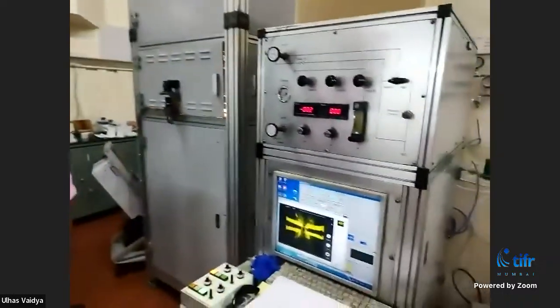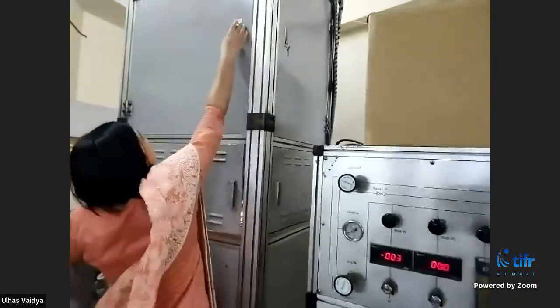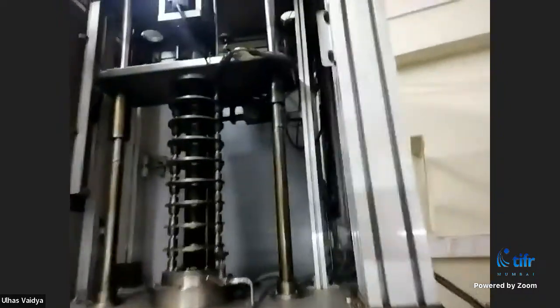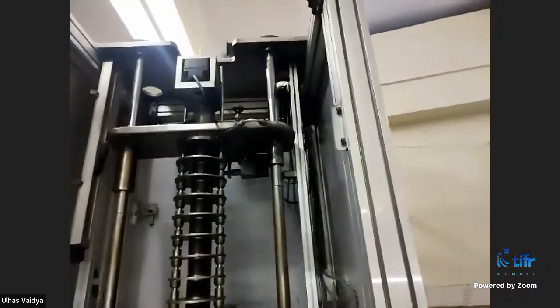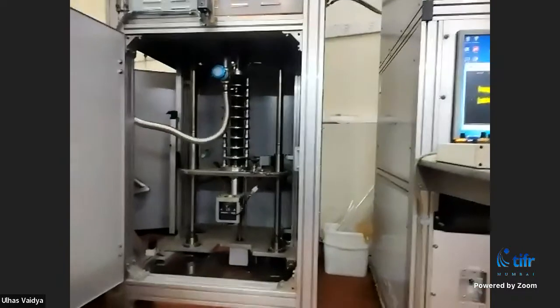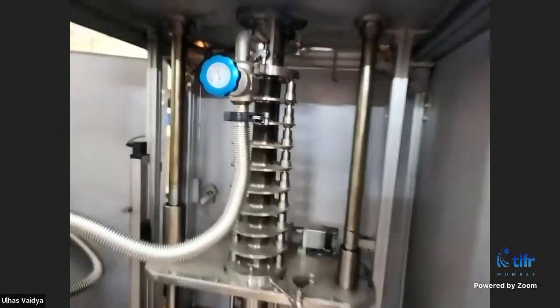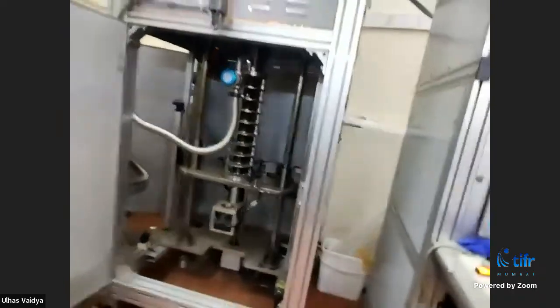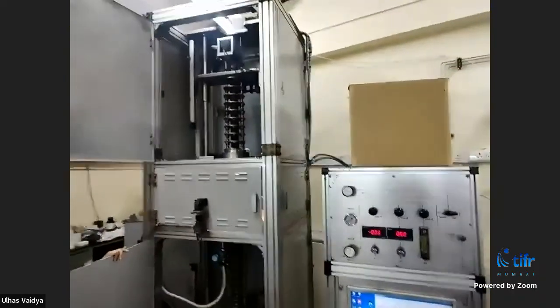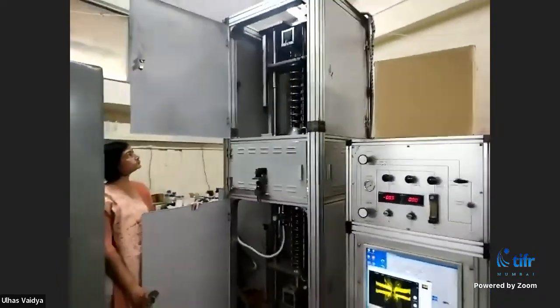And how does one get this slow speed? So there is a stepper motor inside, and it can control the speed actually. This is how you can see from inside. This is how it looks. There is a top stepper motor, and we have a similar one at the bottom also. You can see that there is a valve there to pump out the gas, and then we close this valve, and we can put any gas inside, either oxygen or argon plus oxygen. Those kinds of mixtures can also be put. And the top one is the feed rod moving mechanism.